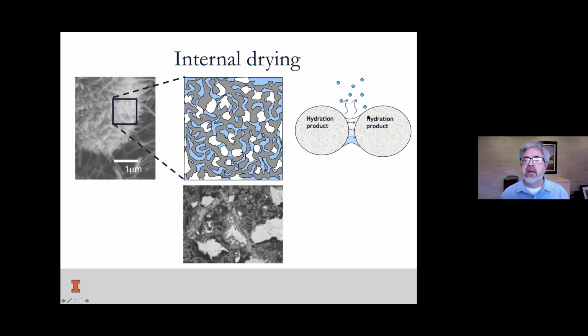And the picture on the right shows liquid water bound between these two surfaces, and then a meniscus, and then water vapor out here. That is a state of stress, or the origin of the state of stress. So if you want to know why concrete would start to crack itself, go through self-desiccation, this is the answer. These little membranes of water start to feel stress across that membrane, and they exert stress on the solid structural framework of the microstructure. Okay, and then we can talk about the Kelvin-Laplace equation to quantify that in terms of the relative humidity out in this water vapor and the pressure that is being applied.